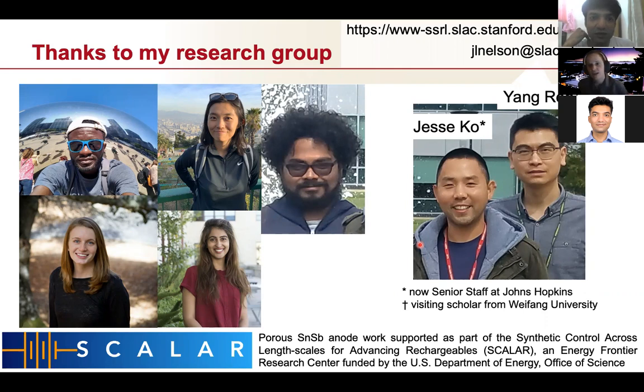Yeah. So I have some published work on lithium sulfur batteries. For TXM, we can see the sulfur dissolve into the electrolyte and whether or not it reforms. We can't reach the sulfur edge for the chemistry imaging on the transmission X-ray microscope, but we do have a scanning probe, which goes to about 1 micron, 2 micron resolution. And there we have done some in situ work at a cross-sectional cell, looking at where the sulfur species, the polysulfide species in the electrolyte,